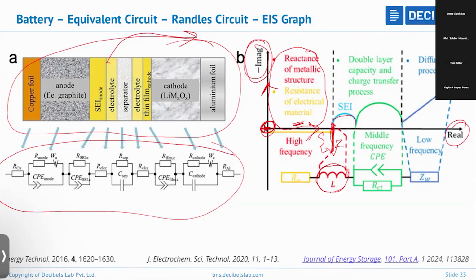Then we have a semicircle, the first semicircle corresponding to the capacitive and the resistive behavior of the solid electrolyte interface. Okay, so they are in parallel to each other, CPE and RCT. Then in the middle frequency, it is because of charge transfer, RCT. Then if you move to very low frequency, there is a 45-degree line with respect to the x-axis at very low frequency that corresponds to Warburg resistance, that is diffusion.